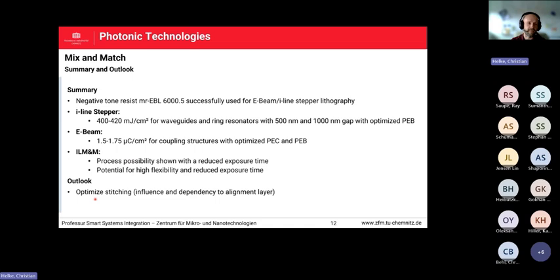So as a small summary for the mix and match approach, I showed you some results regarding the negative tone resist mr-EBL 6000.5, successfully for E-beam and I-line. For I-line, we had a process window of, let's say, 420 millijoule per square centimeter for the waveguide and the ring resonators, with 500 nanometer and 1000 nanometer structures. And for the E-beam, we had an optimized proximity effect correction and PEB, of course. And the dose we needed here is just 1.5 to 1.75 microcoulomb per square centimeter, quite low.